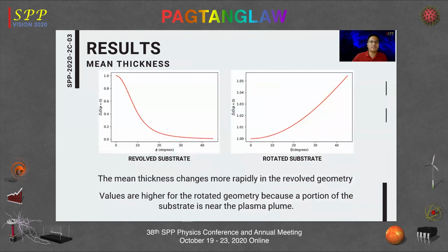Also, the shape of the profile changes more gradually as the angle increases for the rotated geometry. Now, looking at the mean thickness, as you can see in this figure, for the revolved substrate, the mean thickness decreases rapidly as the angle increases. Okay. And on the other hand, for the rotated substrate, the values for the mean thickness change by a very small amount, although it is increasing because a portion of the substrate, again, is nearer the plasma plume than the other portion of the substrate. Okay. So the values are higher than 1.